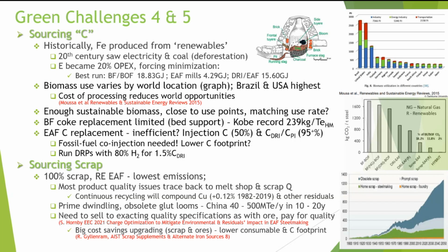And one of the other issues is replacing the carbon in an EAF. Currently, the average is about 50% efficient, and I'm saying efficiency by combustion definition. If you're injecting, it's 50%. If you have it as an in situ carbon in either pig iron or DRI, it's 95% or more.